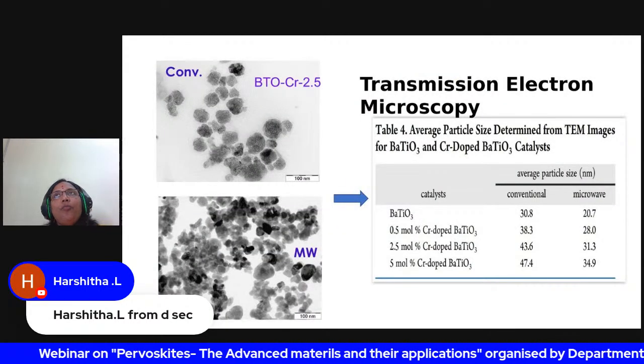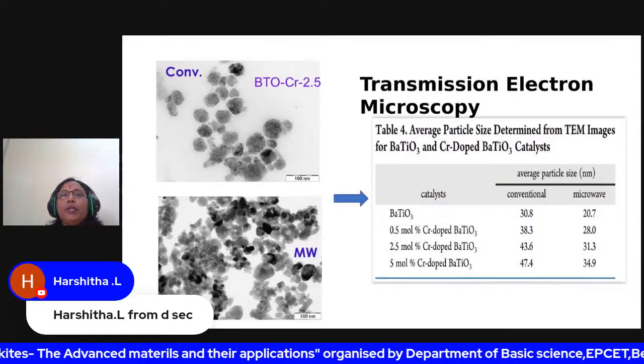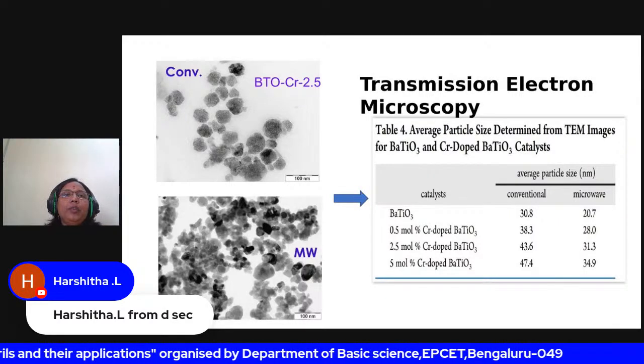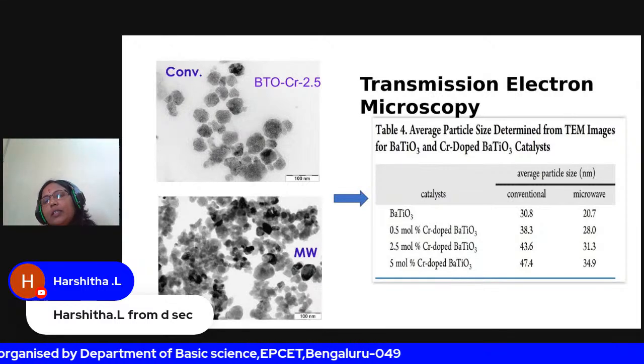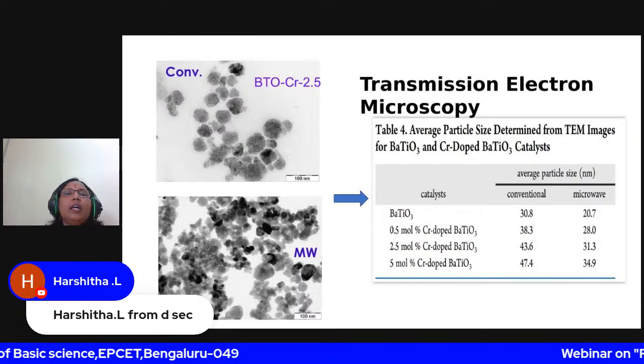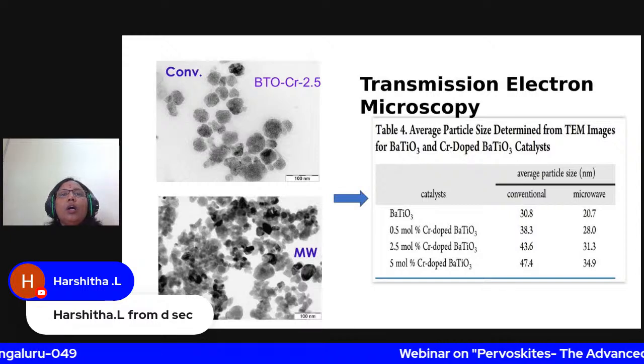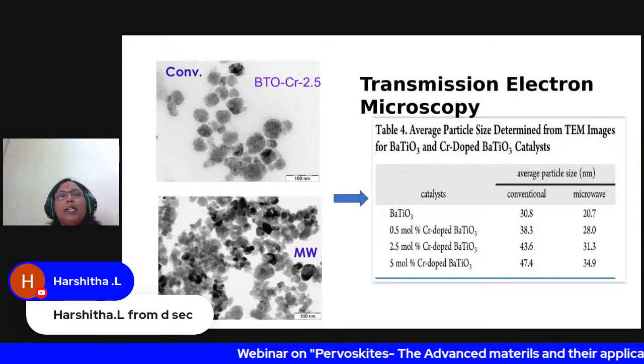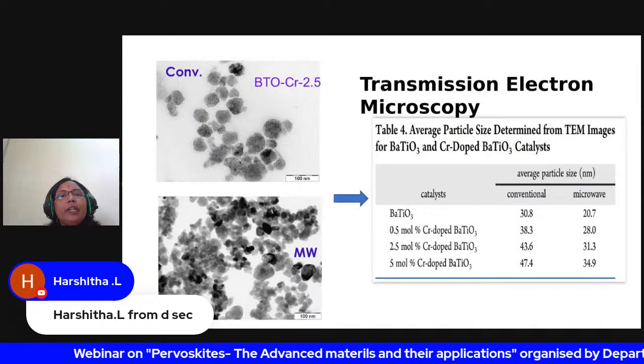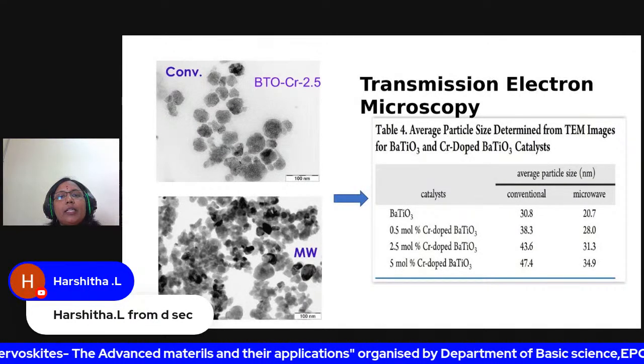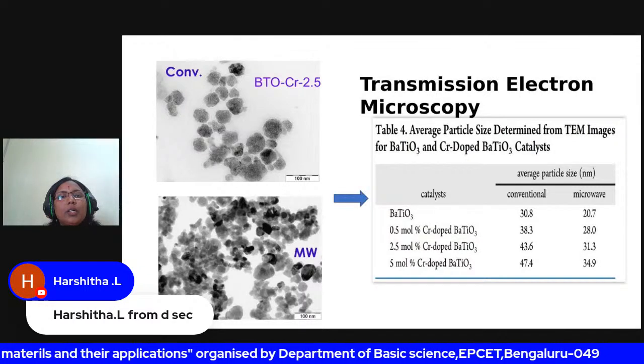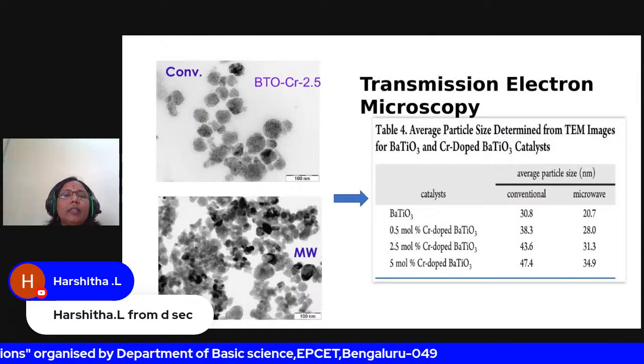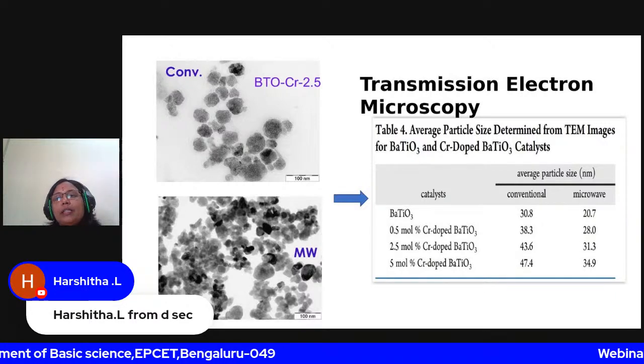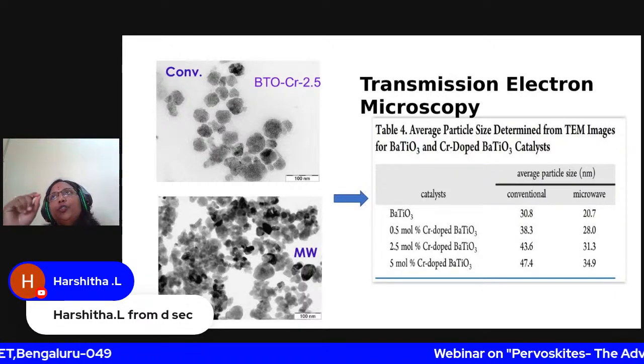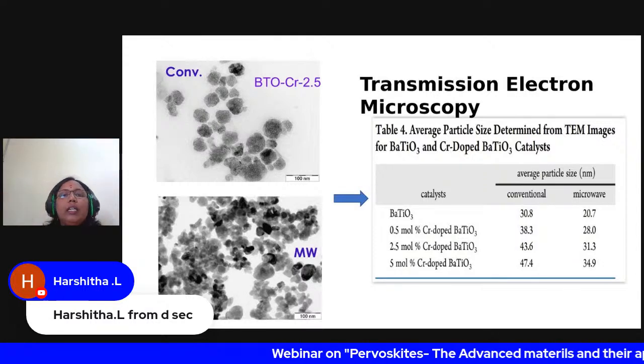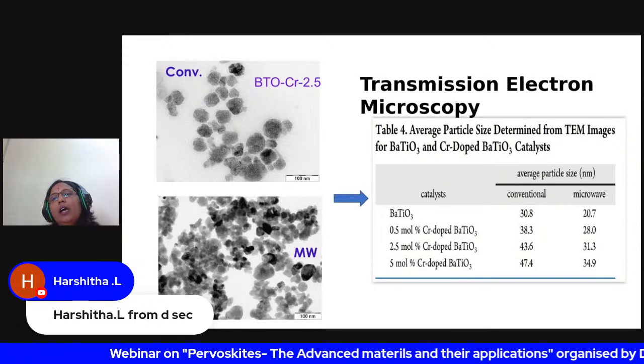Okay, so the morphology and the particle size determination was conducted using transmission electron microscopy. For example, I didn't give all the data here because it will take time. Just as a sample, I have given the 2.5% chromium doped barium titanate sample. You can see here the particles are very large and lightly agglomerated, whereas the microwave synthesized sample shows smaller particles and they are nicely distributed over the sample. For particle size determination, there is a tool, a scale tool, and using that tool you can always calculate the particle size.